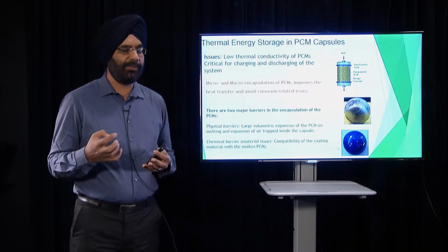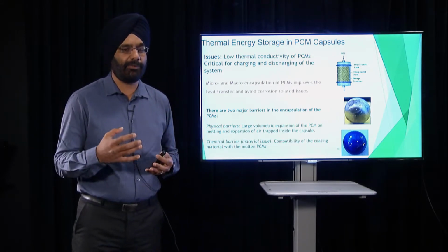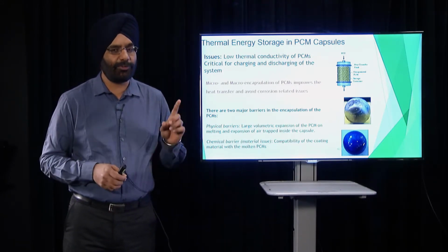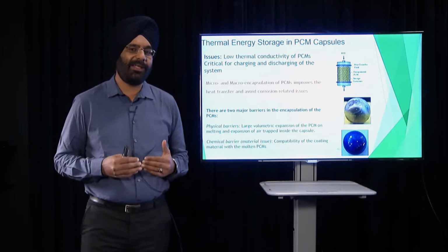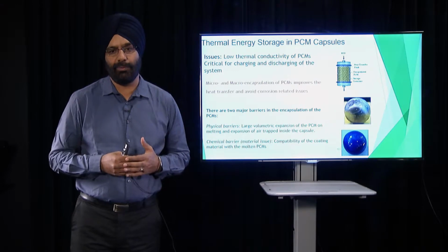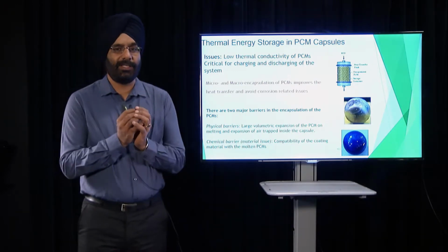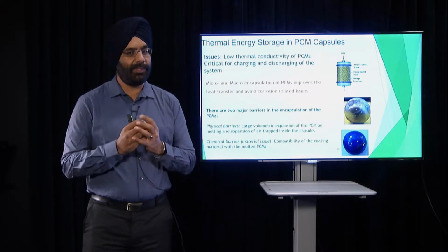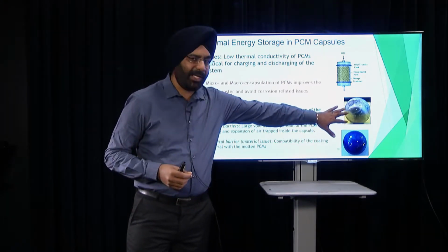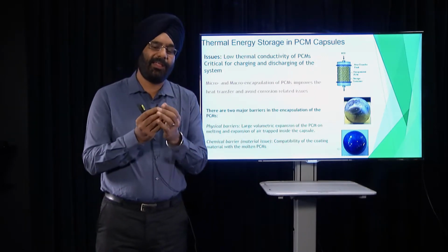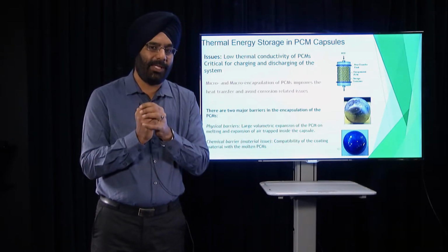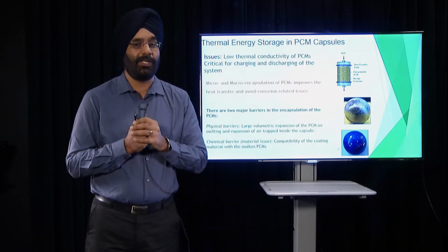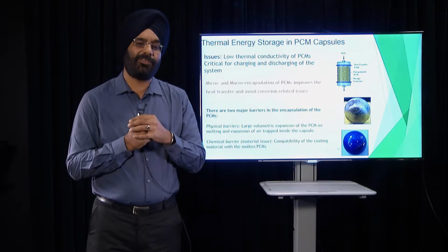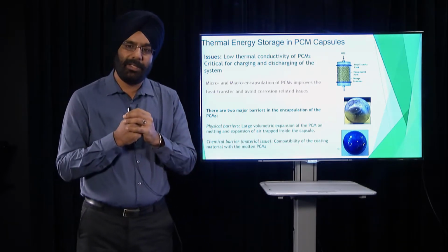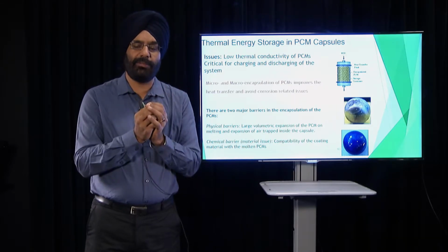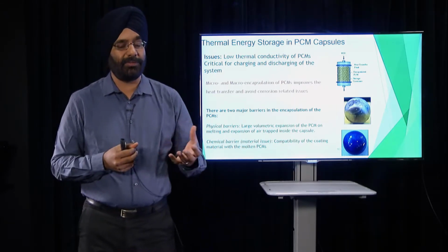But with phase change material, we are going from one phase to another, from solid to liquid. When a solid gets converted to a liquid, there is a huge expansion of the volume and a decrease in density. So the material expands. If you have a rigid encapsulation, it is going to generate pressure inside the capsule. And if this pressure is higher than the strength of the encapsulating material, it is going to explode. The coating is going to crack. So this is the physical barrier.